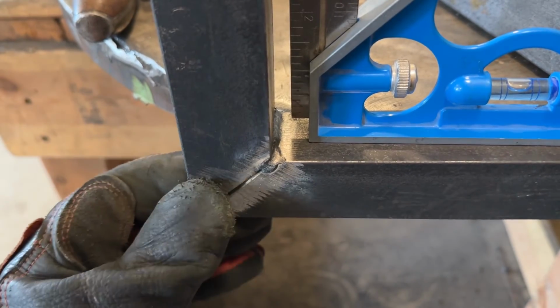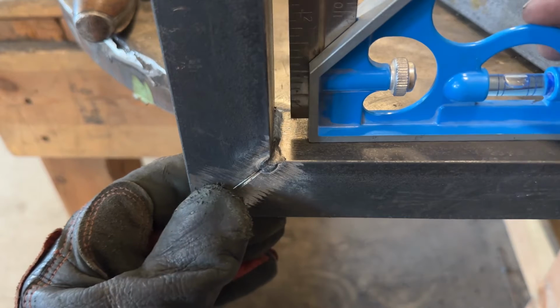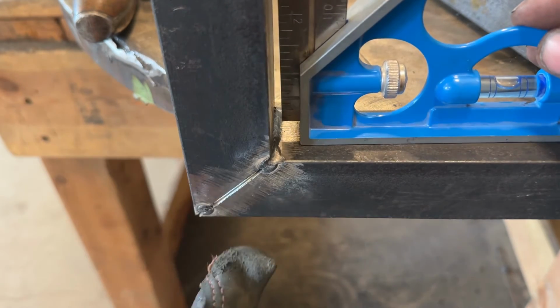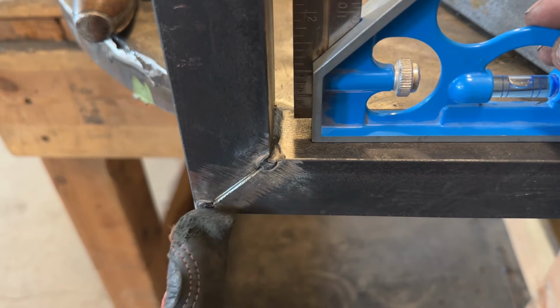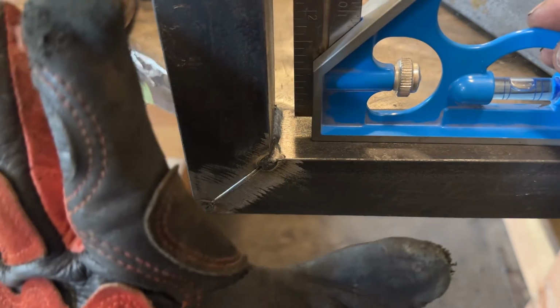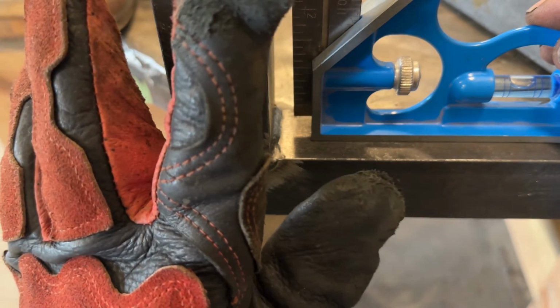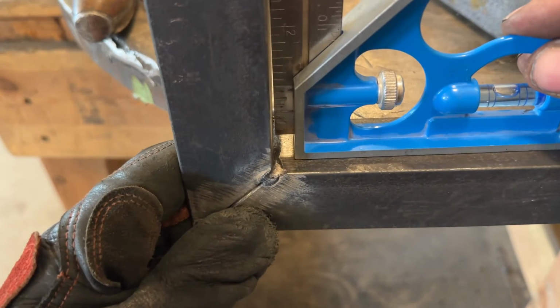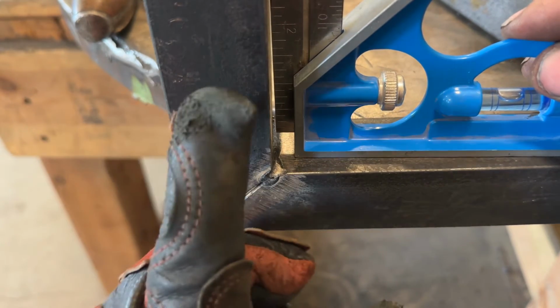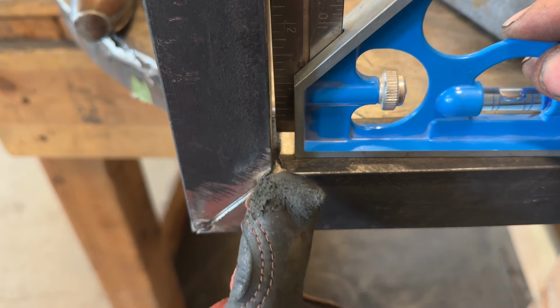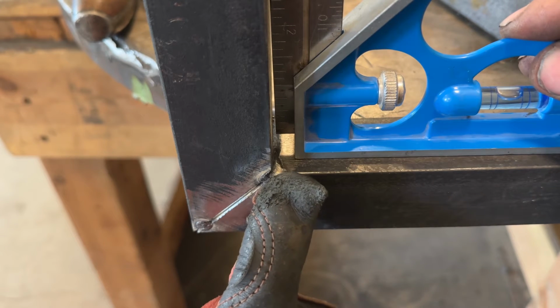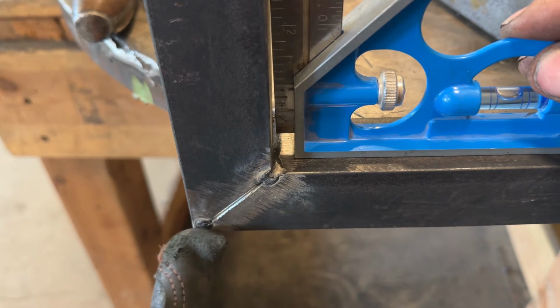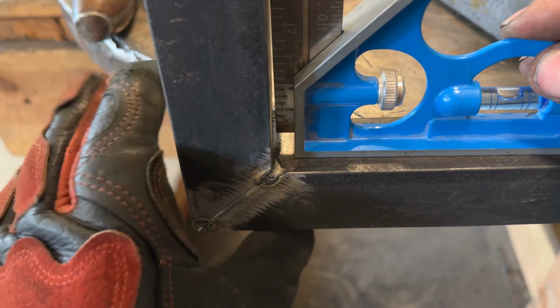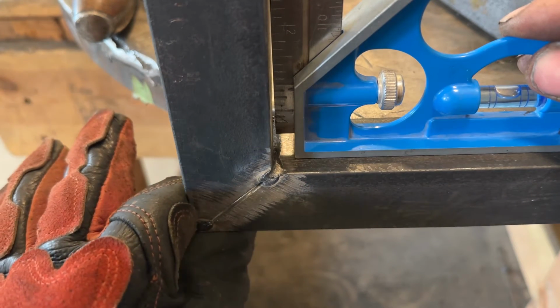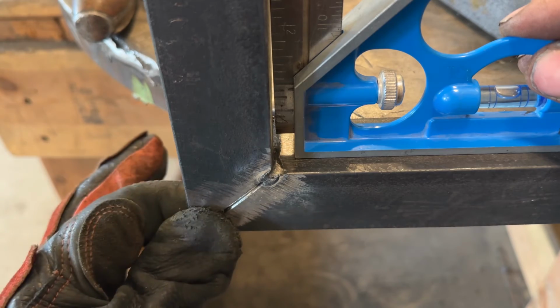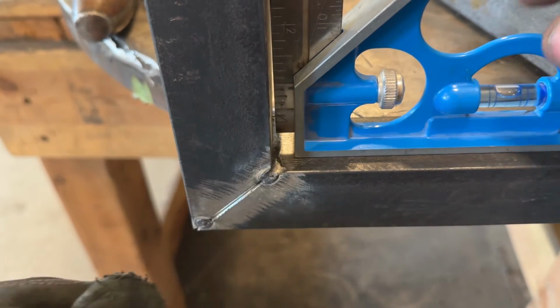So I went over to get a sip of coffee and heard a pop, and guess what? Mistakes were made. This bottom tack broke because this shrunk so much, it pulled it over, and look, that's how much that weld pulled it out of alignment. But we're actually still in okay shape. What I'm going to do is grind this out a little bit so that I can squeeze this a little bit closer to straight. We're going to re-tack it, and then we're going to recheck it.